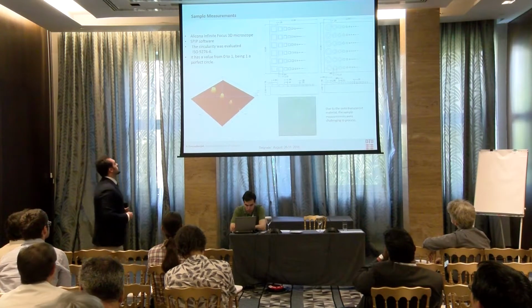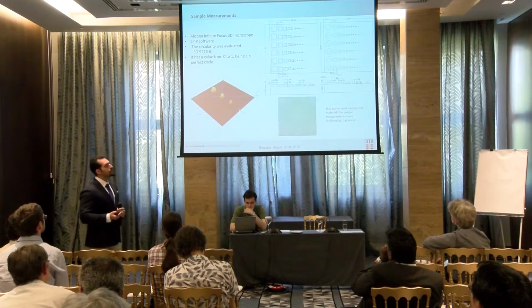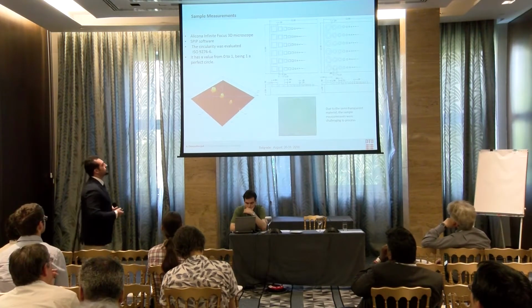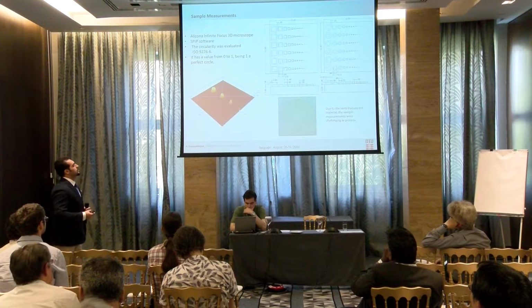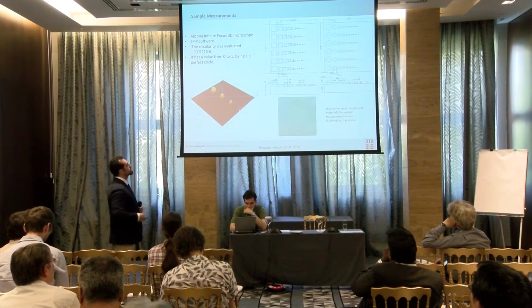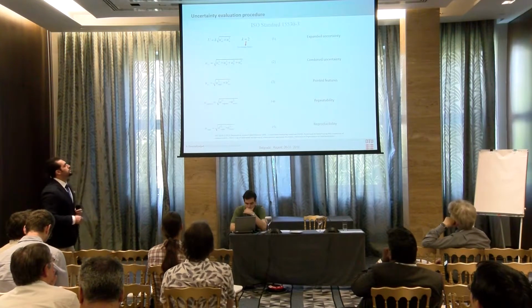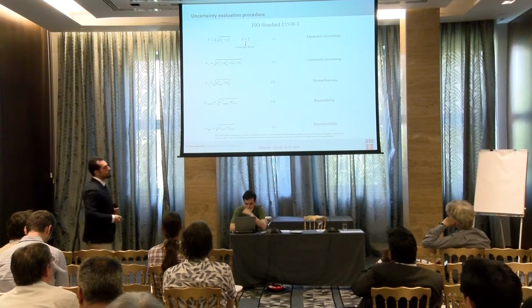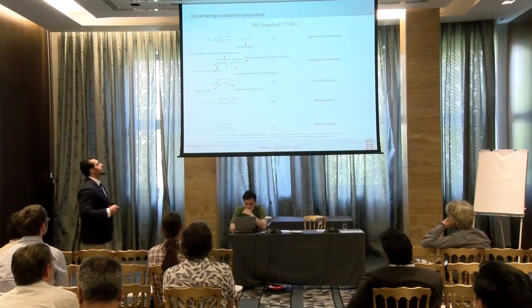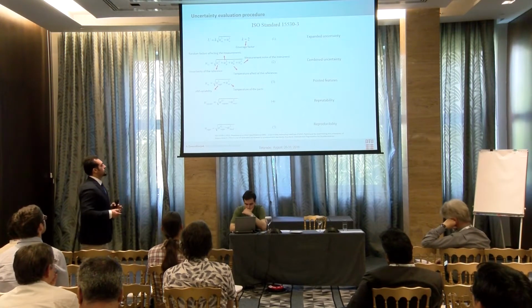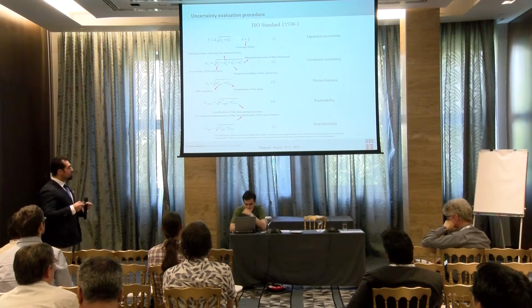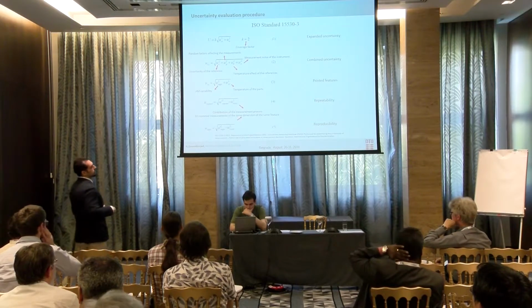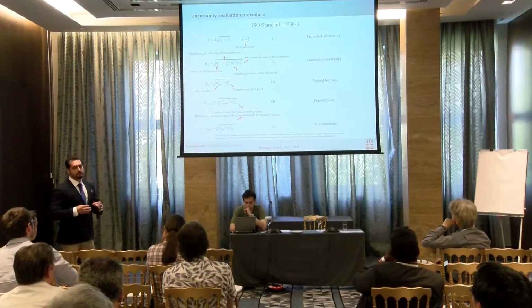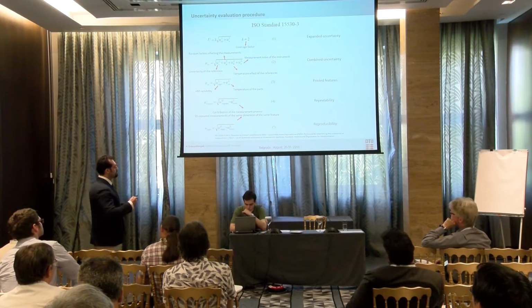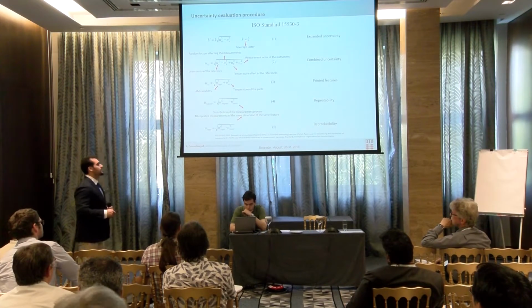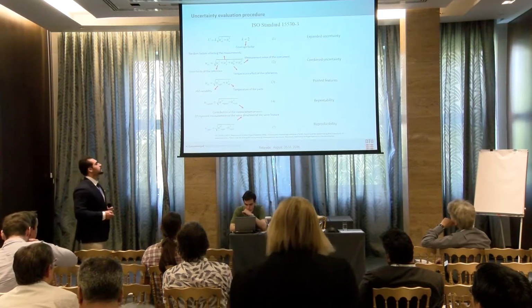The Alicona Infinite Focus 3D microscope was used for the measurement of the features, and the SPIP software to evaluate the result. The circularity and squareness mainly were checked for the printed features. Apart from that, the uncertainty evaluation procedure was applied based on the ISO standard with coverage factor 2, which expands the uncertainty to 95% coverage of the whole printed samples. The temperature effect was not considered because the measurement was applied in a standard room with constant temperature. And then finally, repeatability and reproducibility of the additive manufacturing machine was considered.